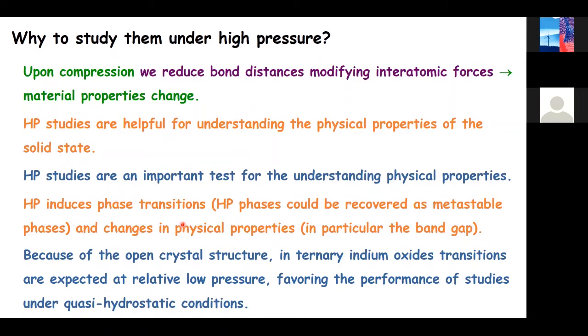So then why do we study them under compression? The main thing is because under compression, we reduce the bond distance, modifying the interatomic forces. This usually leads to important changes in the material properties. That way, high pressure studies are very helpful for understanding the physical properties of the solid state and also for testing the understanding we have of the properties at ambient pressure. The models that we have developed for ambient pressure, if they are correct, they should also hold for high pressure conditions. Another interesting thing is high pressure induced phase transitions. In some cases, it could be metastable, and we can recover the high pressure phase at ambient conditions and induce important changes in the physical properties in the materials of interest.